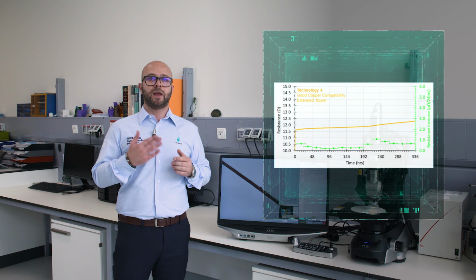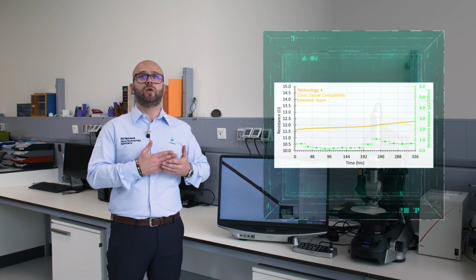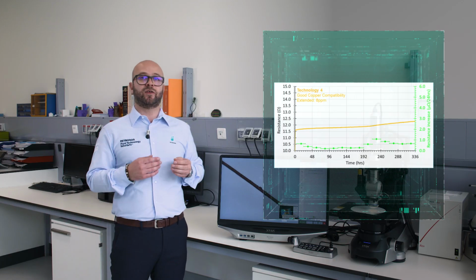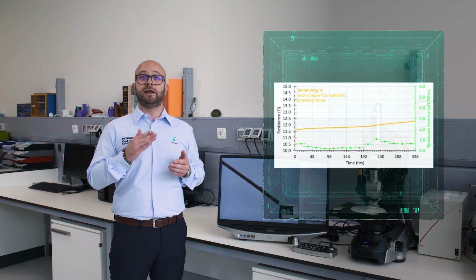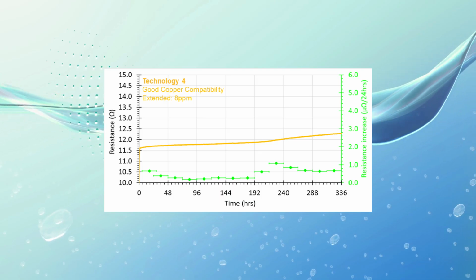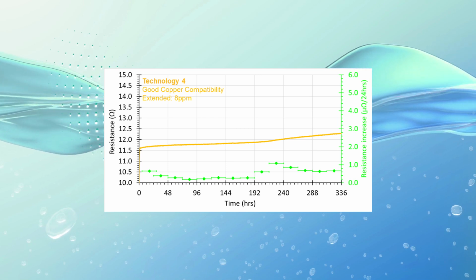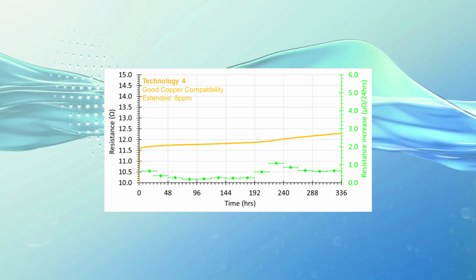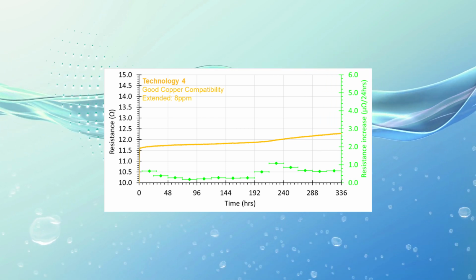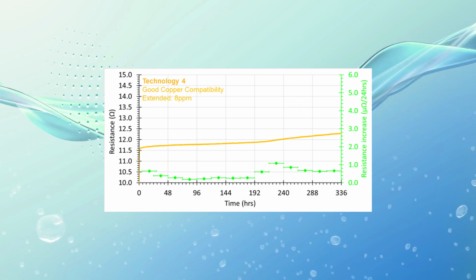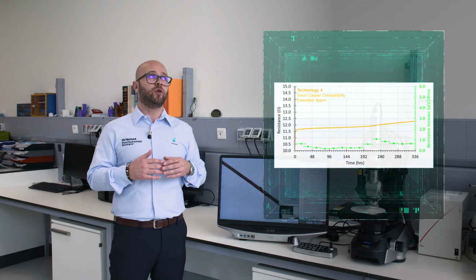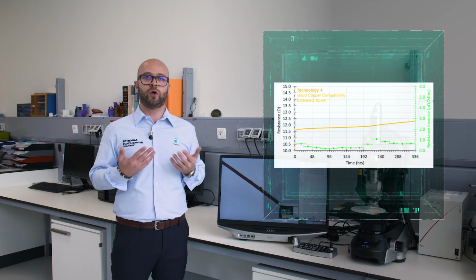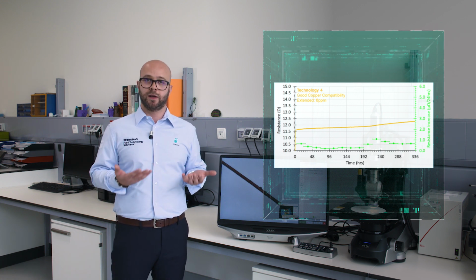Technology 4 is able to complete the test, so we reached 336 hours without any issue. Also, the rate of increase of resistance is very low and gets stable over the time. We have a final increase, however, situation is much more stable compared to the technology 2. So in this case, we can say that we have a good corrosion resistance.